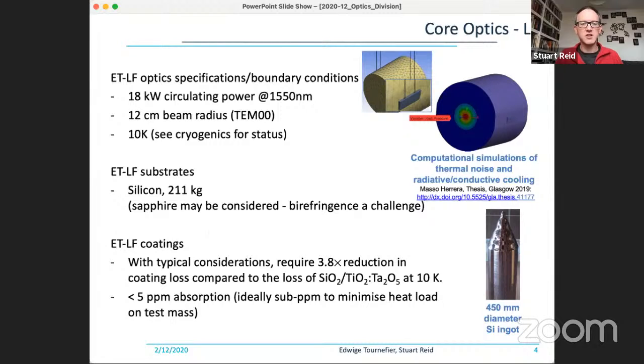performances. The substrates, we expect to use 211 kilogram single crystal silicon, but as was highlighted in the previous discussions, there's not currently a supplier of this size of silicon ingot, and there's no supplier for ingots that have greater diameter than 450 millimeters. And so we are either reliant on industry developing this or setting up a lab ourselves. But there's a lot of work within industry trying to push the optical properties of these very large silicon ingots. But of course, sapphire is still on the table as a consideration. There's also a lot of modeling that's being done for how these cryogenic suspensions will operate. So I just cite one of those there, but many groups are working on that.